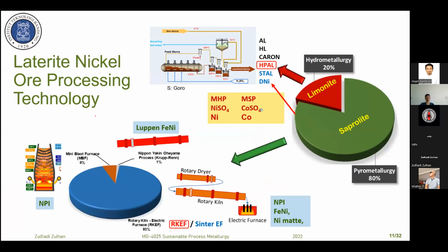This data is actually similar to before. If we're talking about laterite nickel ore, there are two types, saprolite and limonite. The limonite is now processed via hydrometallurgy. The current proportion is around 20% or even less, because most of the RKEF plants are now built in Indonesia, with a capacity of more than around 1 million tons of nickel per year. And saprolite nickel ore is processed via pyrometallurgy. A couple of years ago, the data showed that around 80% of laterite nickel ore was processed via pyrometallurgy, but I think the current figure is higher.